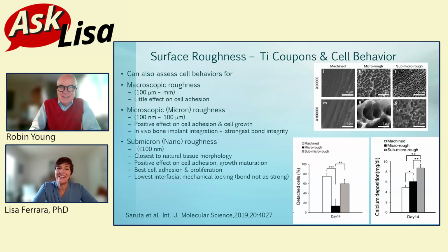You have to understand, microscopic cellular size is 10 to the -6, nano molecular is 10 to the -9. But studies have shown, and this is one by Saruta, and I thought this was very interesting because we've done a lot of work, I remember when I was at the Cleveland Clinic as well, looking at programmed cell growth on different surfaces, nano and micro. And this study looked at surface roughness. Now we talk about surface energy, and just because it's rough, you're going to increase the surface energy. But now we're distinguishing between micro and nano.